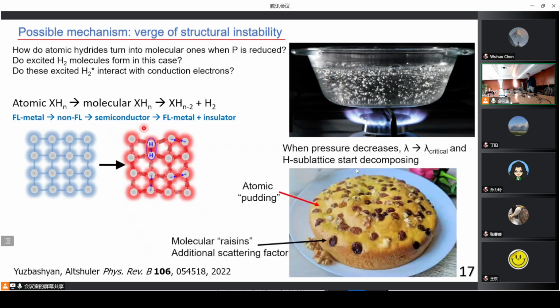We can increase temperature, or we can decrease pressure. In our case, in the case of hydrides, we decrease pressure. We decrease pressure, and the hydrogen sublattice starts decomposing. And after that, the situation looks like pudding with raisins inside. We still have atomic pudding, the hydrogen sublattice, and it demonstrates some superconducting properties.